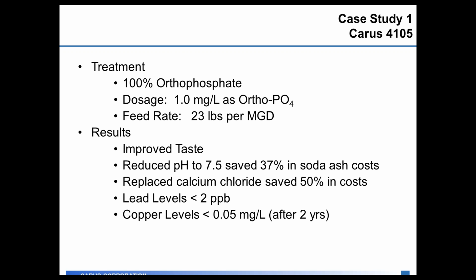What did this lead to? They had improved taste. They weren't getting customer complaints for metallic tasting water out in the distribution system with the addition of the orthophosphate. They eliminated their red water complaints in the distribution system. Their lead levels dropped to less than 2 parts per billion, so well below the 15 parts per billion action level. And the copper levels dropped to 0.05 milligrams per liter after 2 years. So the treatment change worked across the board, providing better water quality to the consumer in the distribution system.